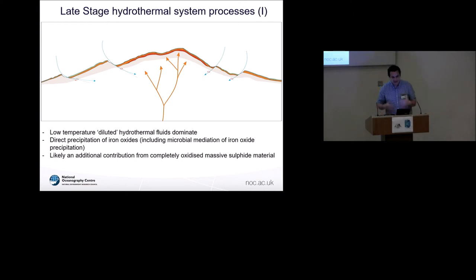So to discuss these as processes themselves, the idea is that in all cases we've seen that the iron oxide is forming first, whether it be microbially mediated, weathered sulfide material, plume fallout material, or direct hydrothermal precipitate. That is basically the precursor to this iron silica unit itself. There has to be iron oxide there. And then you can have a result of a low temperature hydrothermal fluid, but it's some degree of mixing with seawater. So at the end of the cycle, the high temperature fluid which forms most of the sulfide materials has started to cease. Maybe the heat source is dropping off. So you've got a cooling of the fluid itself.